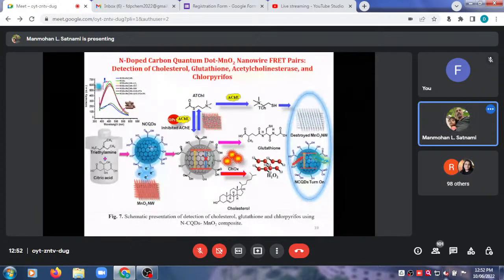Okay, then we prepared MnO2 nanowires using, I think, potassium permanganate. My student can tell better how she prepared, but I think she prepared it through the hydrothermal route. Okay, so we prepared MnO2 nanowire. Then when MnO2 nanowire is added to carbon quantum dot, the fluorescence of carbon quantum dot decreases. It means fluorescence quenching happens. Okay, then in the presence of MnO2, the fluorescence of carbon quantum dot is quenched.